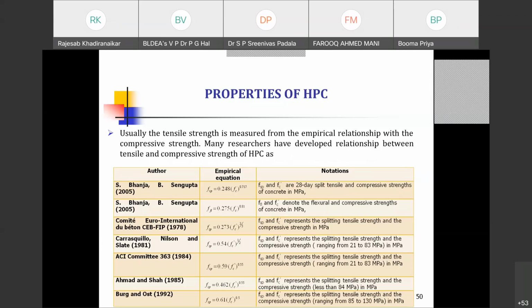Usually the tensile strength is obtained from empirical relationships with the compressive strength. All other strengths, tensile, shear, all those things, we express in terms of the compressive strength. The same you can extend for high performance concrete also. Many researchers have developed empirical equations for finding the tensile strength in terms of the compressive strength, and some of them I have listed here. Whatever expressions you have for conventional concrete cannot be directly applied or extrapolated for high performance concrete. Sometimes they give wrong values or